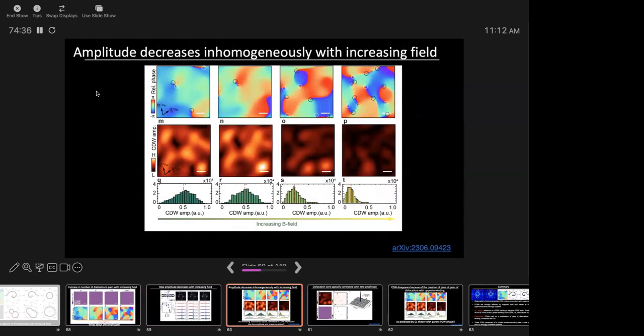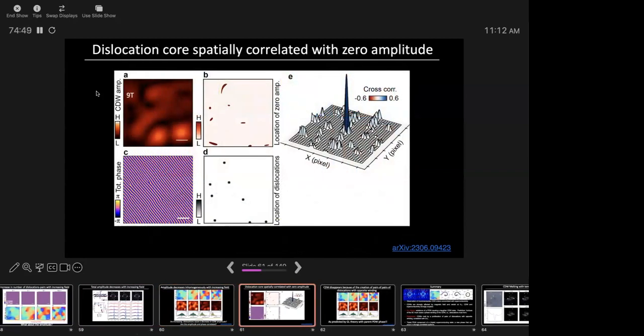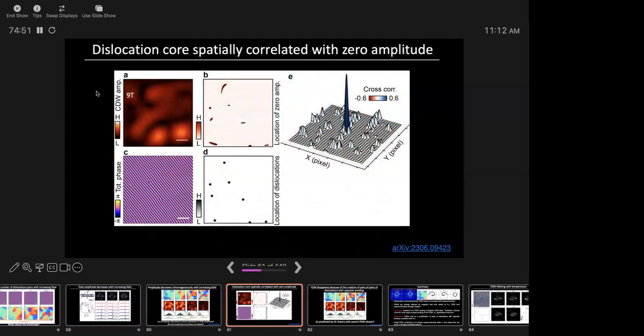And you can see that the amplitude is suppressed, but we can do more than that. What we can do is take this amplitude map and ask, where is the amplitude suppressed? Is the amplitude suppression correlated with the positions of these dislocations? Right here below, these dots represent all the dislocations in this field of view.